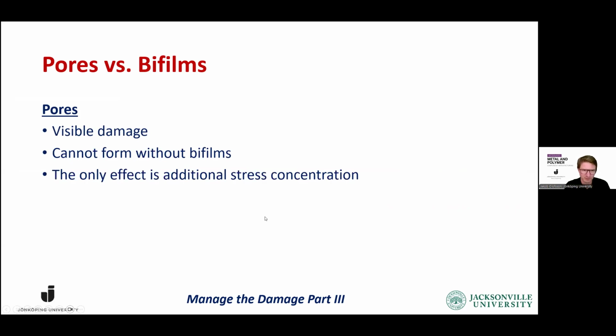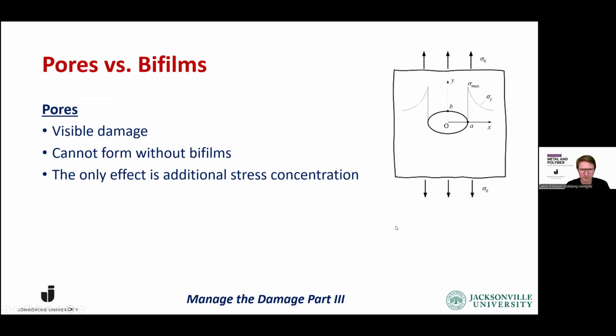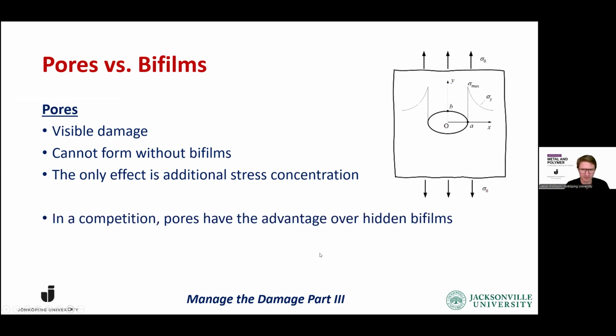And the difference now between what we saw before is that we now also have the pores. So on top of the hidden damage, we also have the visible damage. And as you remember from previous here, these pores cannot have formed without these bifilms. And the effect that they cause is the additional stress concentration that you get on top of what you already have due to the hidden damage. So you kind of inflate the problem here. So in a competition, we will see here that pores will have an advantage over the hidden bifilms, which are smaller and less inflated compared to the pores, which have now inflated the bifilms.